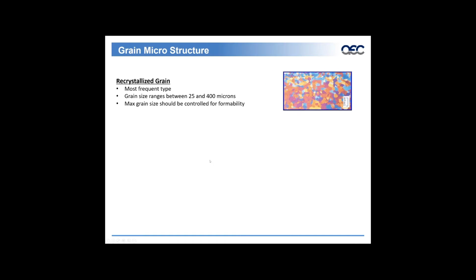A little bit about grain microstructure. We're going to talk basically about three types here today. Recrystallized grain is the most frequent type. Grain sizes range between 25 and 400 microns. The key here is that the max grain size should be controlled for formability.